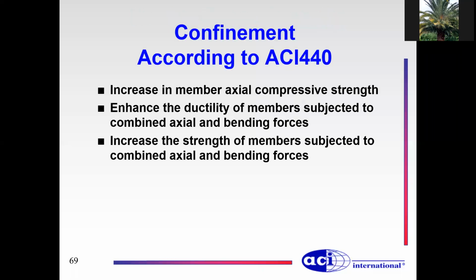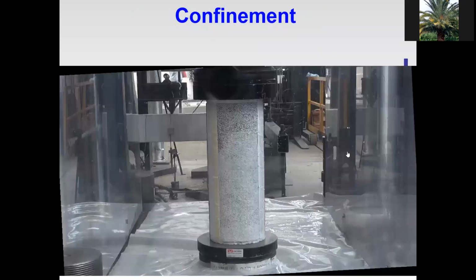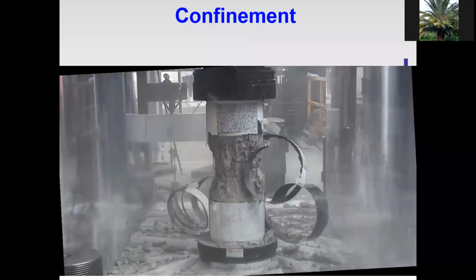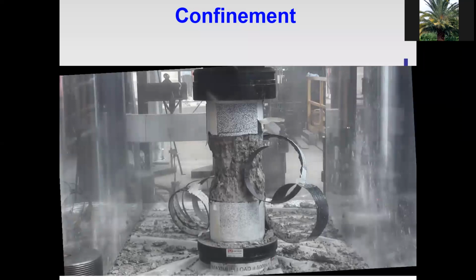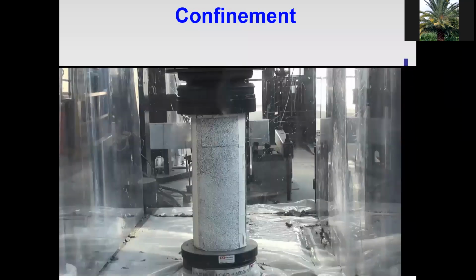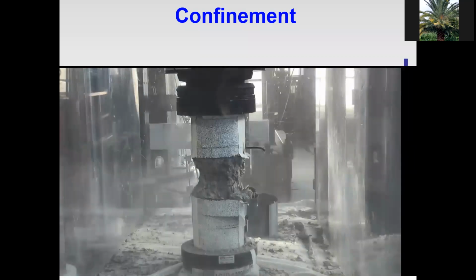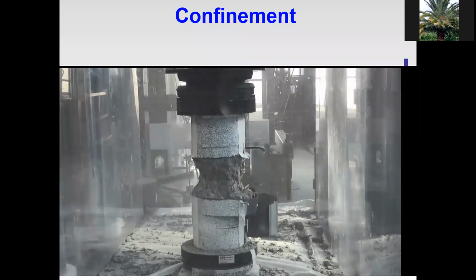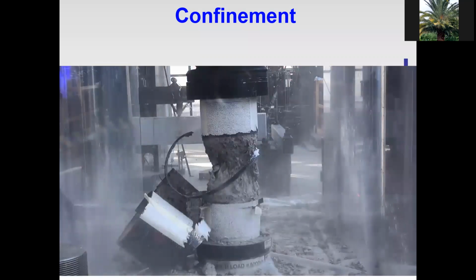The final type of strengthening that we use is for strengthening or confining concrete in compression, what we call, and this is according to ACI 440. Typically, I'm going to show you this video of some of the tests we have done about that. This is a concrete cylinder, unreinforced like that, with carbon fiber. And the capacity of this was more than double the capacity of the concrete itself after we applied this confinement of the concrete.